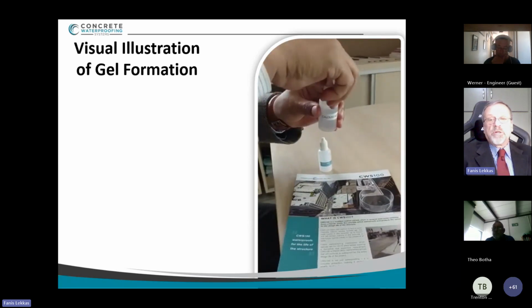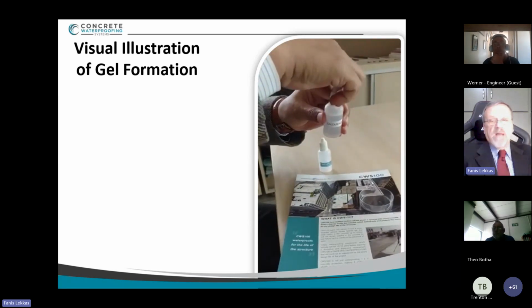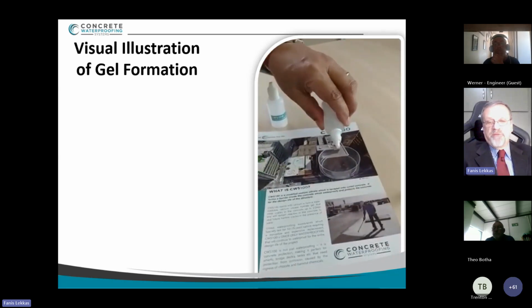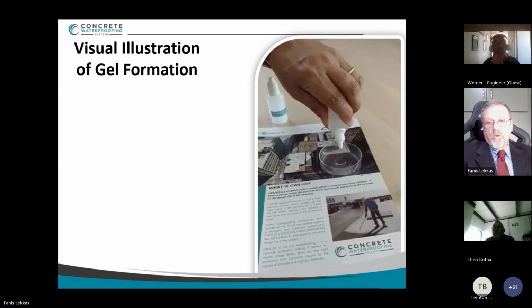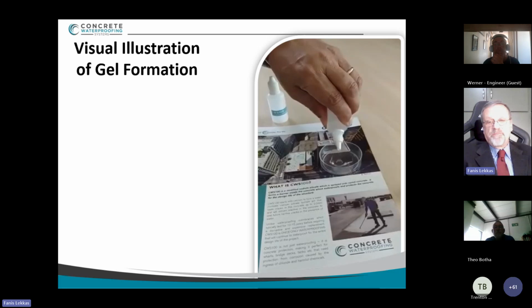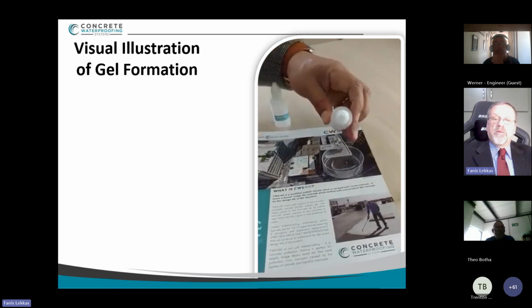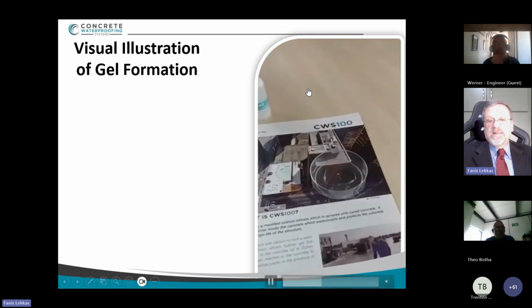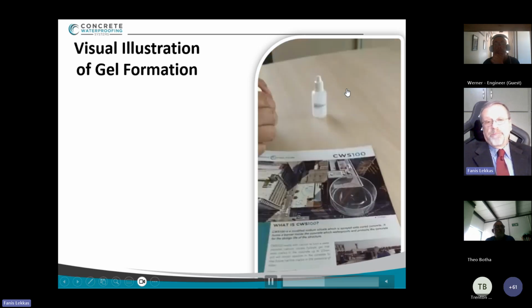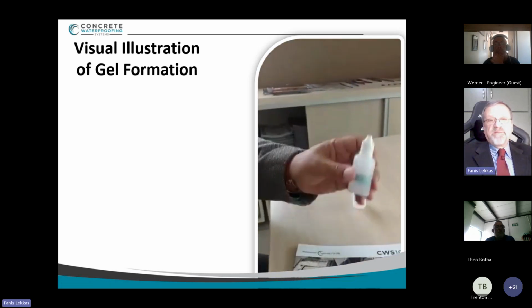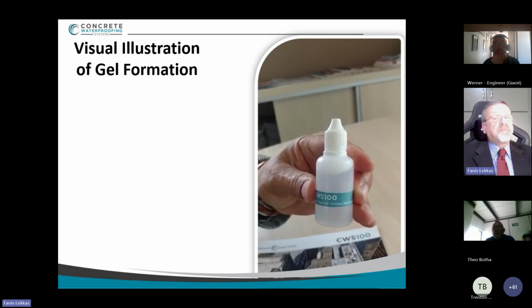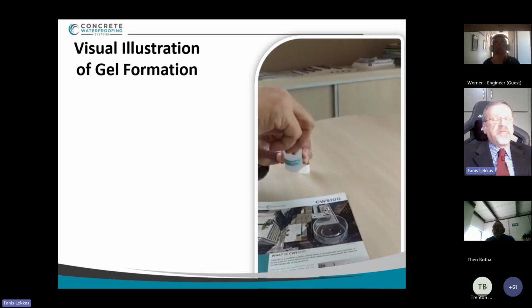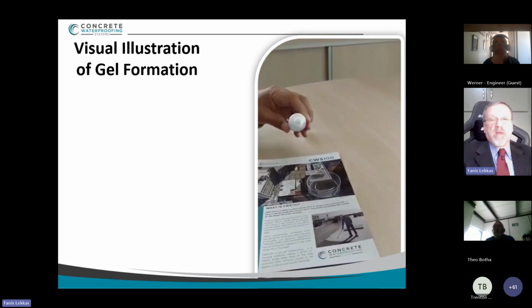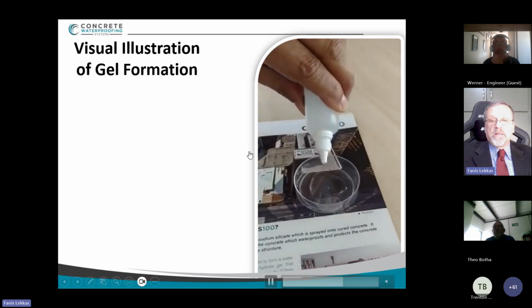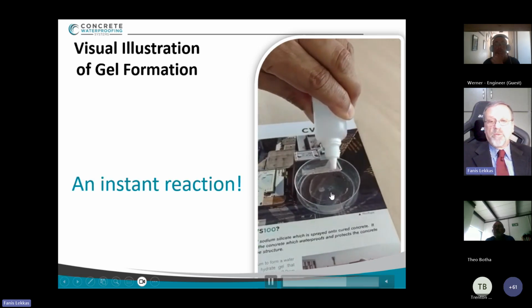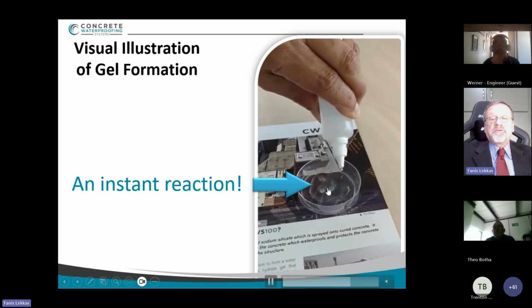Here we have a solution of calcium acetate, some water and calcium to simulate the concrete surface. We put a few drops here in that Petri dish. And then we are going to install the CWS100 product, which is that demo bottle you are seeing back there. You see that these products are liquid, transparent, pretty much like water. The viscosity is pretty much like water. Now have a look. The first drop goes in. Look, 1, 2, 3. You get an instant reaction.